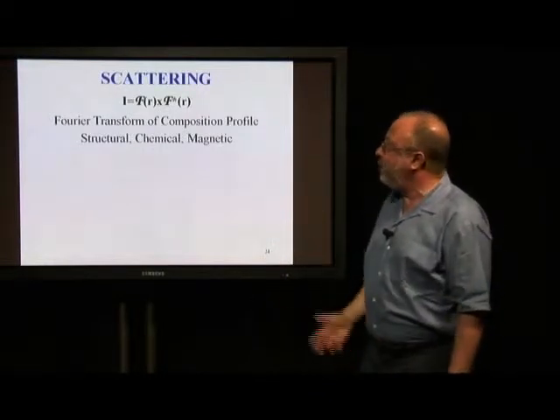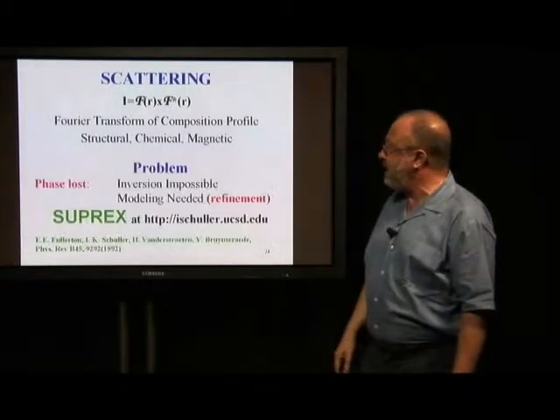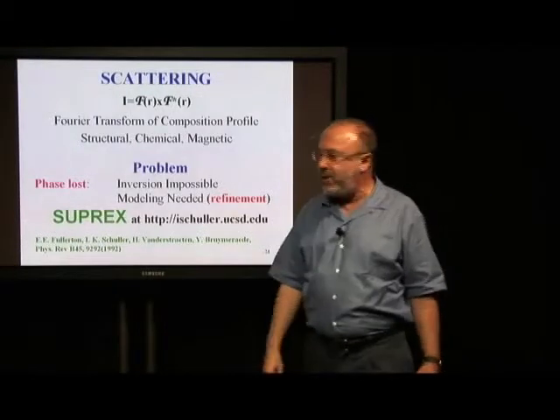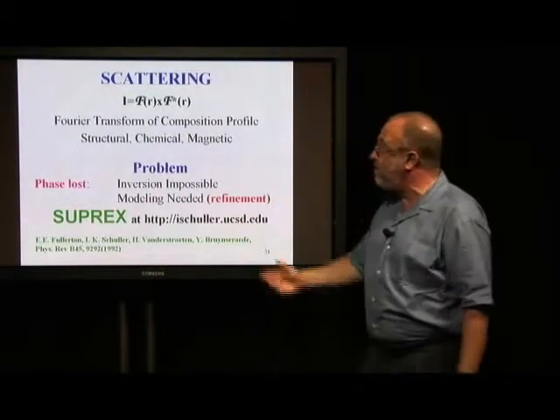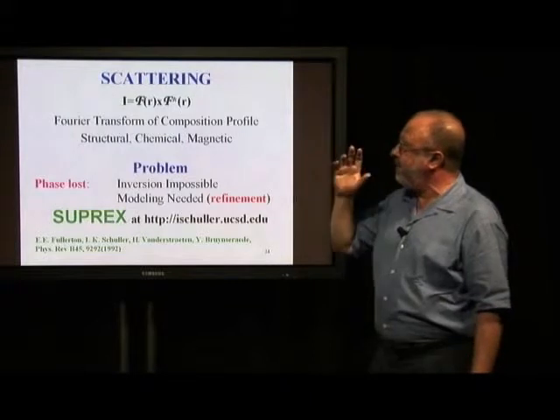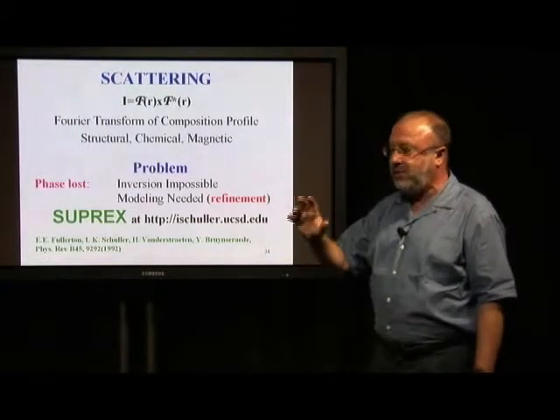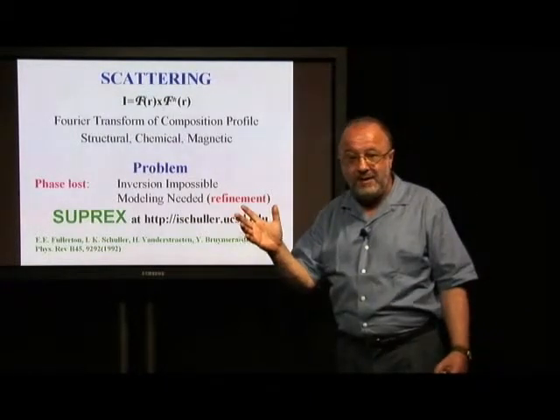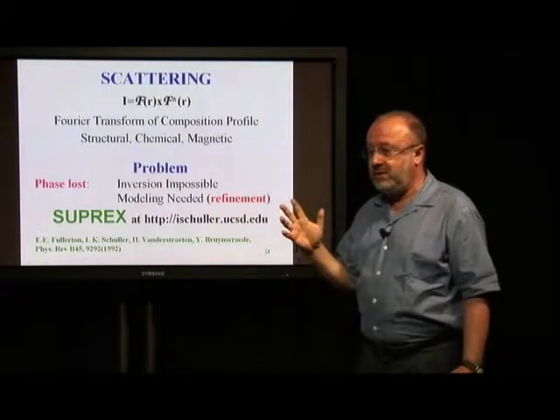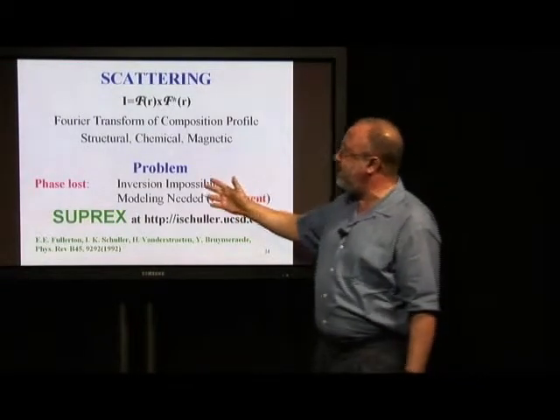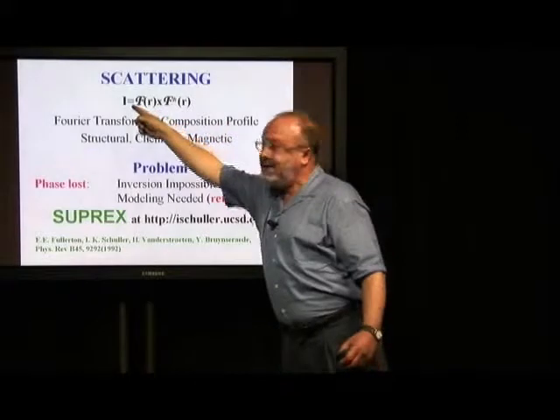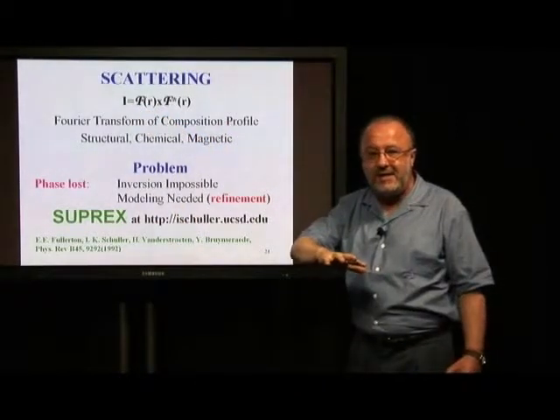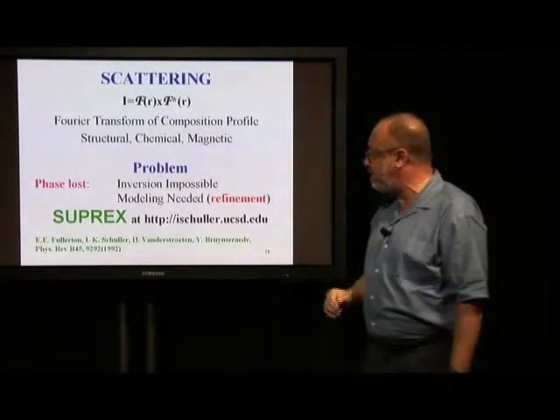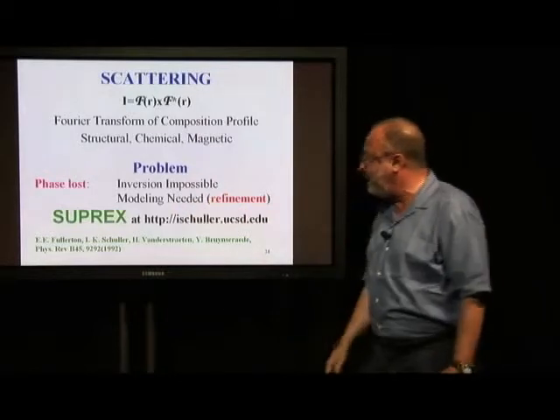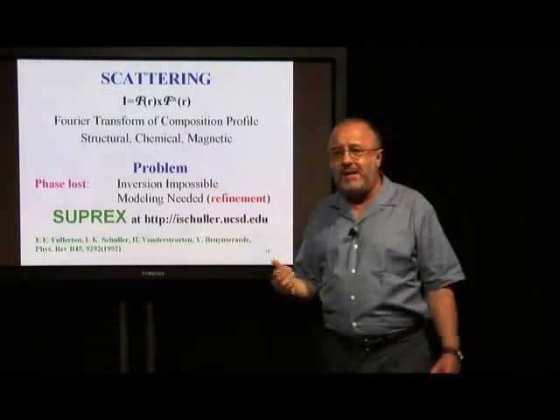Now, it turns out that there is a problem with this, and it is a well-known problem, which is that the phase is lost, because you take the product of the structure factor times its complex conjugate. And because the phase is lost, it is not possible to take the intensity and invert it directly to get the structure. That is not possible. So one needs to do what is called a refinement. And this is well known for bulk materials.